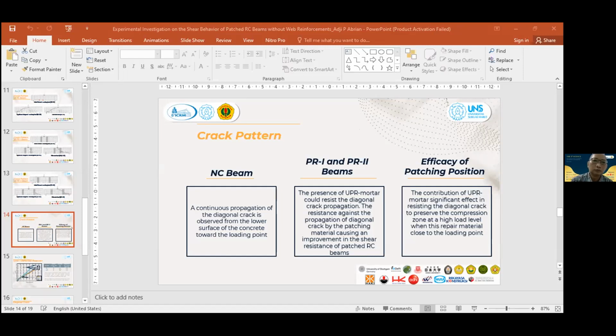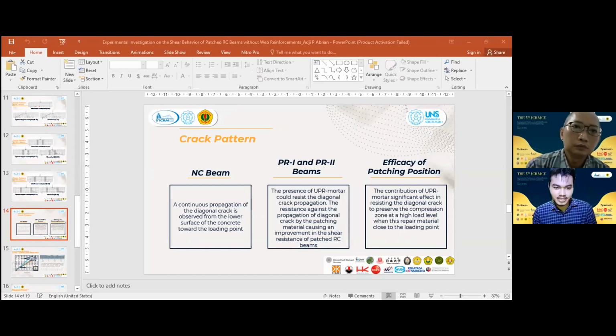Okay, that's my opinion. The presence of patching can influence the shear transfer mechanism. The high tensile strength of the patch repair material effectively prevents the diagonal cracks from propagating, and consequently, the beam holds a sufficient compression zone to provide a considerable Vcy. And furthermore, in the diagonal crack beam, the uncracked UPR-mortar provides slip resistance, promoting better aggregate interlock on the surface of diagonal cracks and improving Vcy. Thank you.